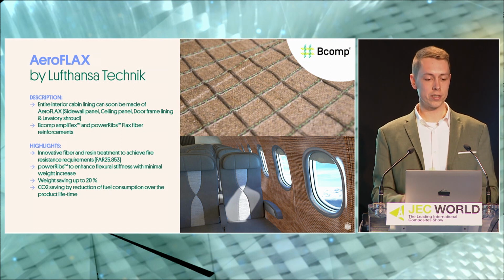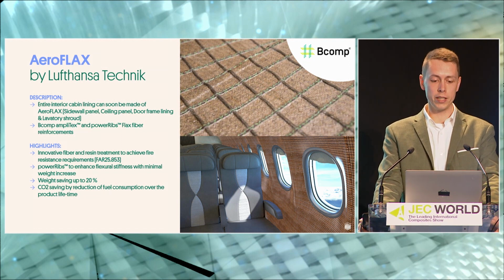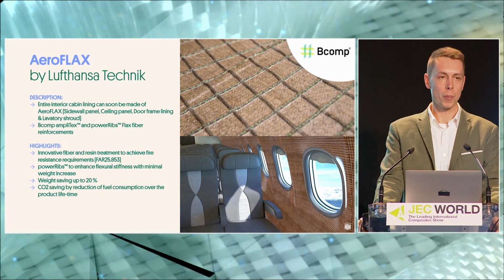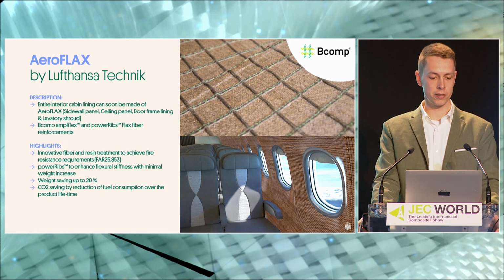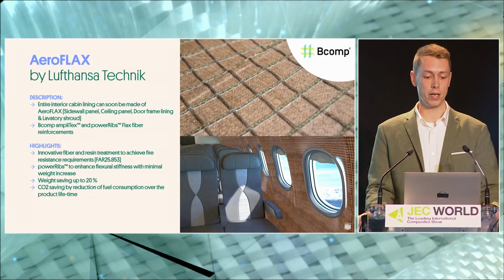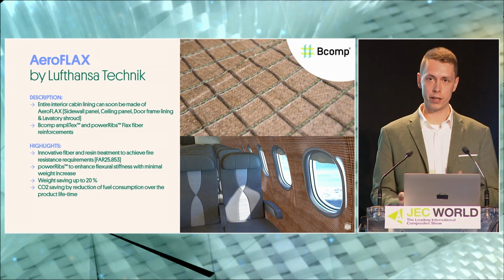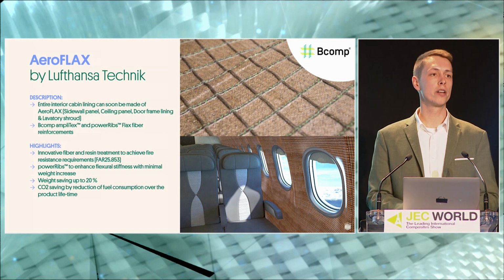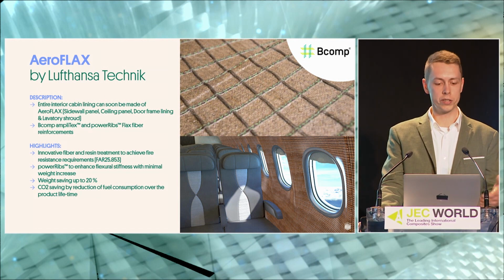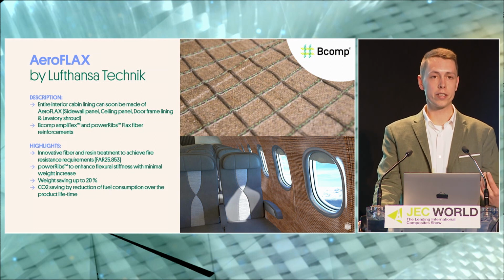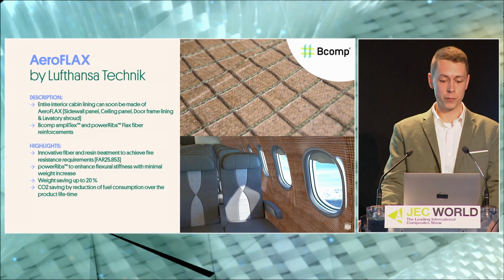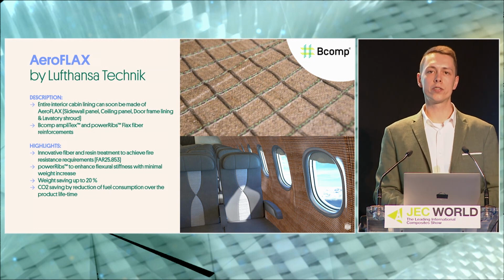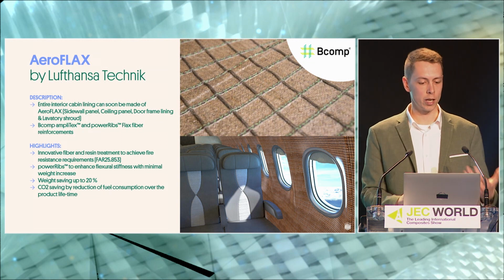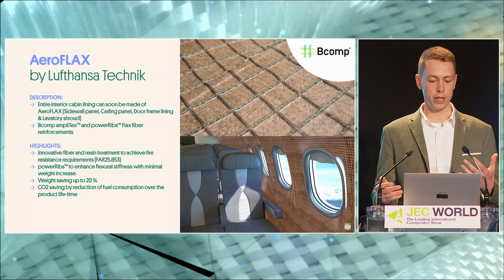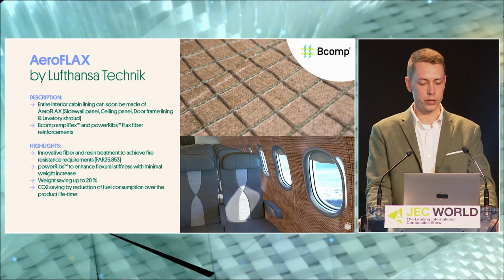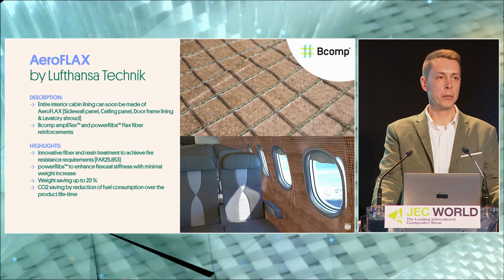So it is also very interesting that soon the entire cabin lining can be made of flax fiber composites. And here in this example, B-Comp Amplitex and B-Comp Power Ribs reinforcements were used. And with an innovative fiber treatment and an innovative resin treatment, B-Comp was able to achieve the fire-resistant requirements in the aerospace. And with using these innovative flax fiber reinforcements like Amplitex and Power Ribs, they increased the flexural stiffness of the composite parts with a minimal weight increase.